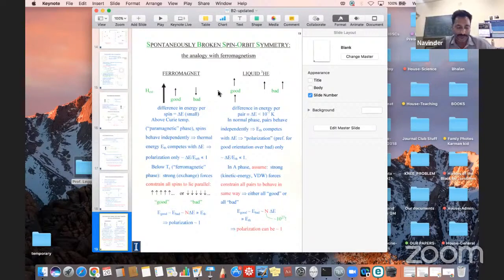My question is related with this NMR. In a BCS superconductor, we have this Hebel-Slichter peak below Tc, a rise in the NMR relaxation rate, and on the other hand, if we look at the ultrasound attenuation, it shows a decrease. That is understood due to the BCS coherence factors. Do we have a similar analogous phenomenon in helium-3, a Hebel-Slichter kind of phenomenon?